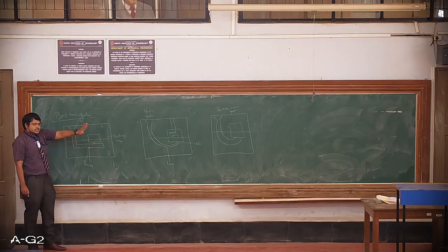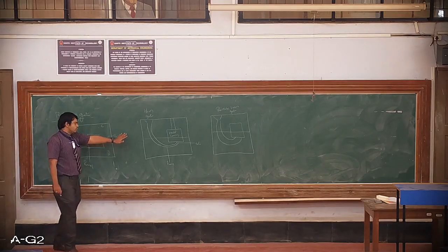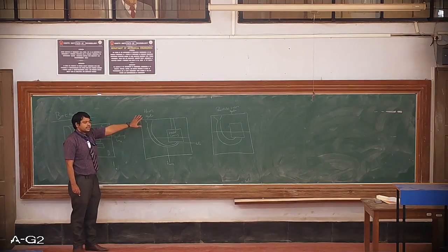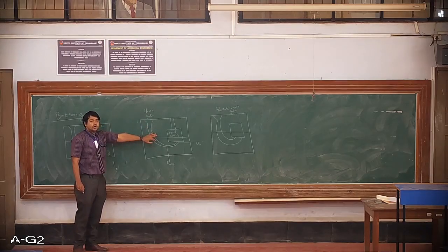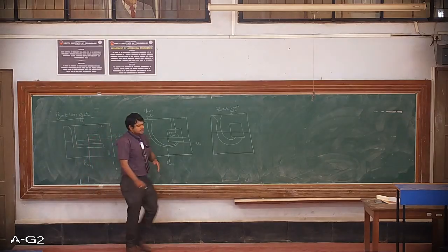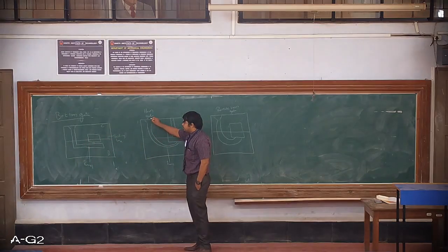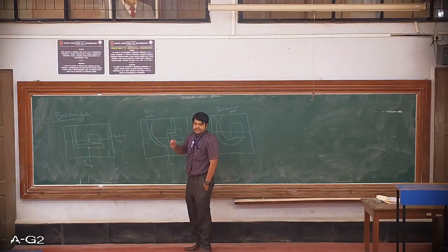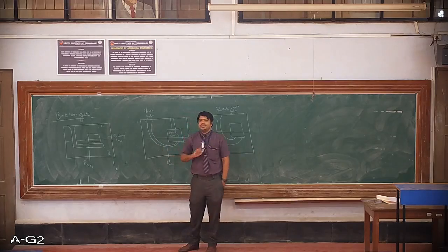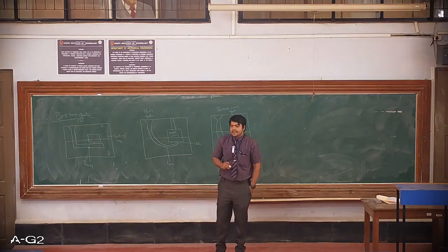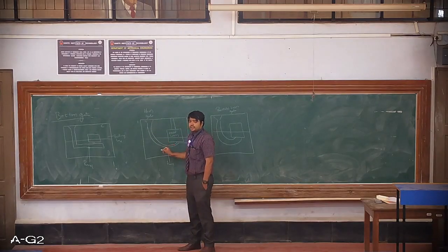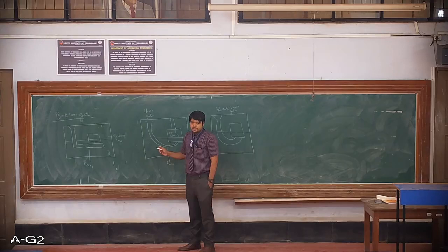In certain castings with a complex geometry, we generally make use of this particular part called horn gate. As this geometry resembles the horn of an animal, we call it horn gate. Here what happens, the molten metal is made to enter the mold cavity with this particular curvature. Here the sharp edges are not there, so sand erosion problem will be automatically reduced, and as the metal has to travel a longer distance, the gas entrapment will also be reduced.